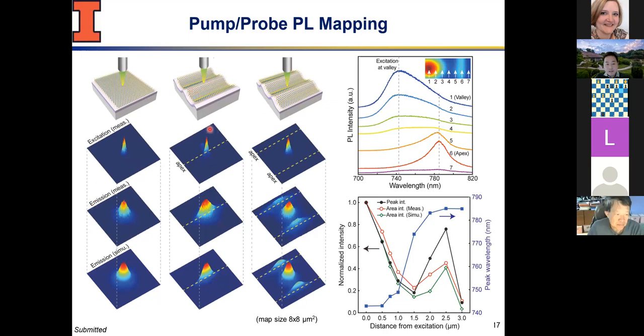So at the apex, it's the same circular beam. But then if you look at the emission pattern, it is no longer circular. It looks like it's a bit squeezed, perpendicular to the long axis, that's the dotted line, and it's more spread out along the dotted line. So that's the first observation. Interesting. And when you pump at the valley, the middle point between apexes, so no light is actually being pumped into the apex, you see a circular beam emission, but you also see additional satellite peaks at the two apex positions. This was never expected.